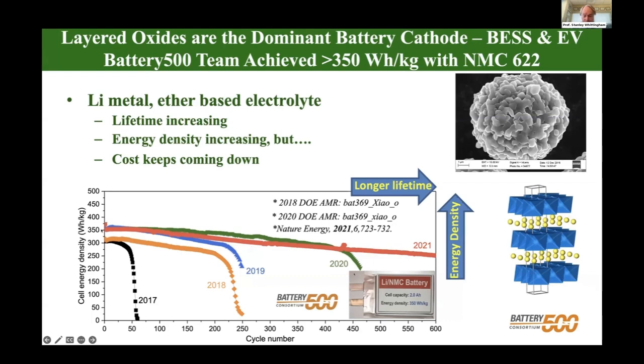And I show you the typical pouch cell we're using for these tests. Pouch cells are made in Washington State and go to Idaho National Lab for testing. So all the actual energy densities I show you here are real energy densities. The cell is weighed and the electrochemistry is measured. So you can see over the 5-year period, from 2017, we've gone from less than 50 cycles at 300 watt-hours per kilogram to, in 2021, 600 cycles. And I'm told right now we're about 800 cycles with 622. I don't think I need to describe what these materials are, so I'll skip that bit. Right now, the baseline for the consortium is 80% nickel, 10% cobalt, 10% manganese.